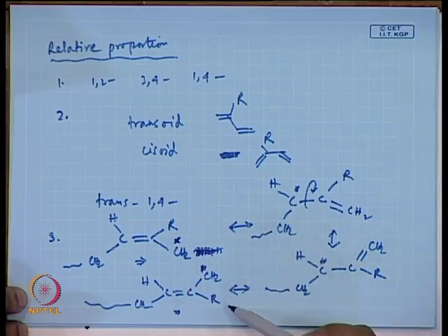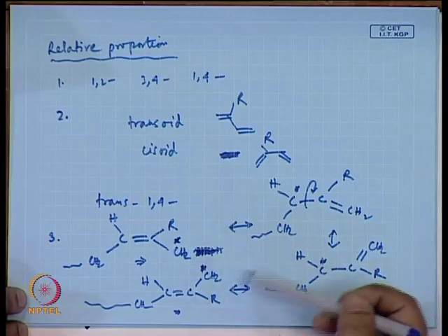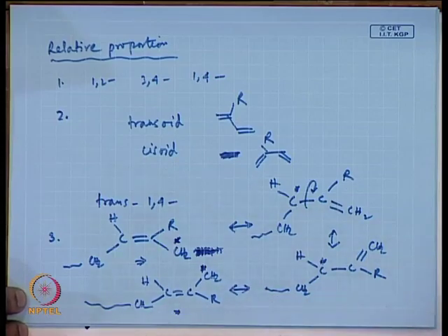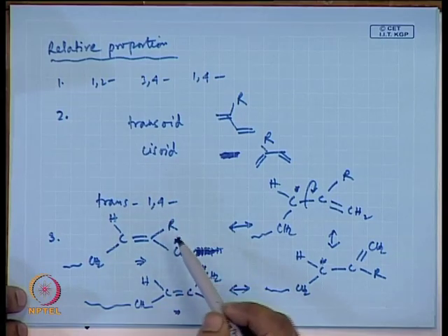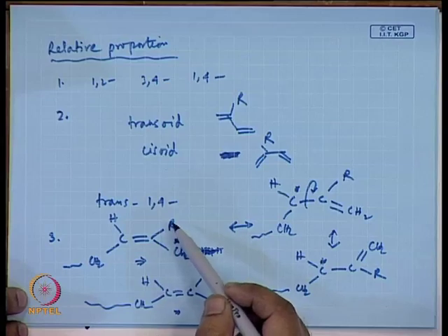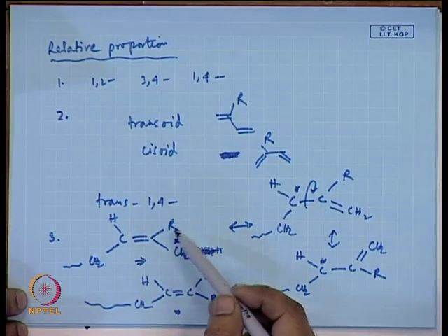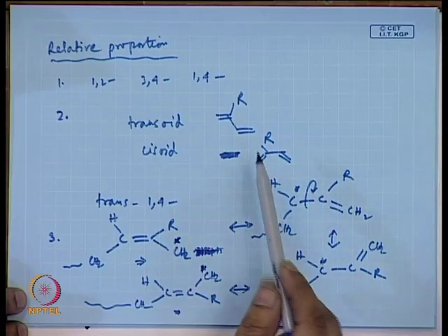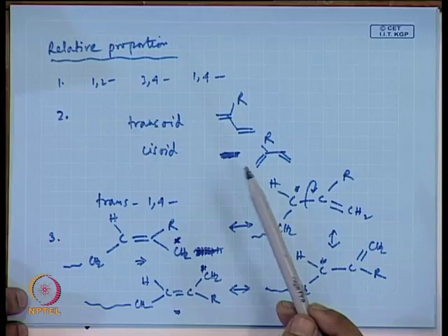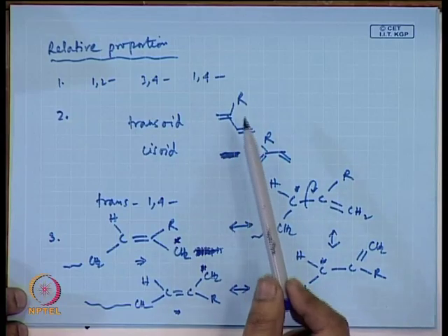If you lower the temperature, obviously this isomerization becomes less and less probable, then the most stable structure, which is a trans structure, will polymerize, which will form the product. Now, if you have this R, depending on the size, obviously you can imagine if R is high, the more the size of R, the trans product will be more dominant, because the energy difference between the cis form and trans form will be much higher as you increase the size of R.